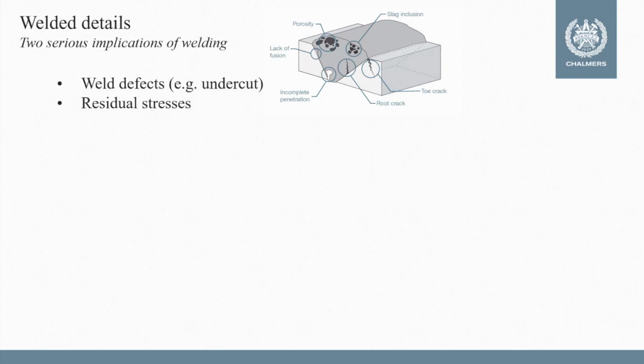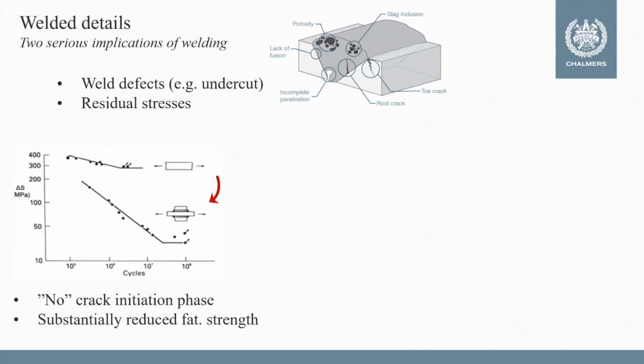The second aspect is, of course, the presence of residual stresses. We assume, and we often get, high tensile residual stresses in welded details in areas which are critical, and that also has its influence and its implication on the fatigue performance of these details. So what these two factors do in principle is that, to start with, they reduce the fatigue strength of the steel, of the base metal, substantially. So we get lower fatigue resistance by introducing these welds.